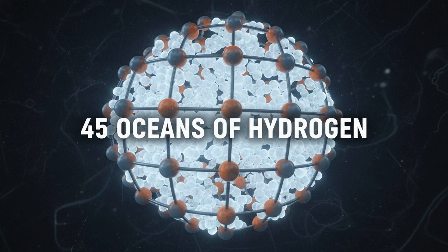The results were paradigm-shattering. The scientists directly observed how hydrogen atoms behaved within the metallic iron. Instead of boiling off or remaining separate, the hydrogen was strongly siderophile, which means iron-loving, under extreme pressure. It aggressively dissolved into the liquid iron, chemically packing itself into the core's material by forming iron hydrides tied to silicon and oxygen-rich nanostructures. The atom probe tomography revealed a surprisingly consistent ratio. For every atom of silicon incorporated into the iron matrix, there was approximately 1 atom of hydrogen.